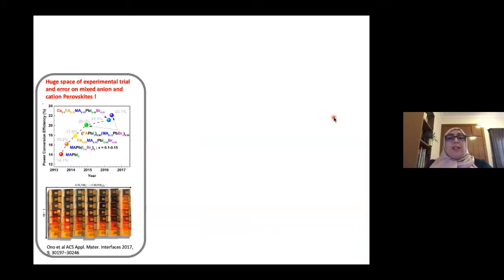The other challenge facing this technology is that here I'm showing some solar cells, and you see the cation sitting in the middle, which is an organic cation. If we change it, we can modulate the optical property, and if we change the halide, we can also change the optical property, the color, the efficiency and everything. This leaves us with a huge space of possible combinations. This is again the power conversion efficiency chart as a function of the years, and you can see that the community has moved from simple chemically processed MAPI material to a mixture of several cations and anions to reach higher efficiencies and also the desired stability.